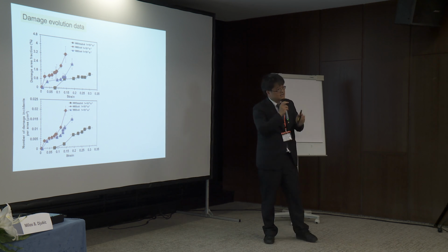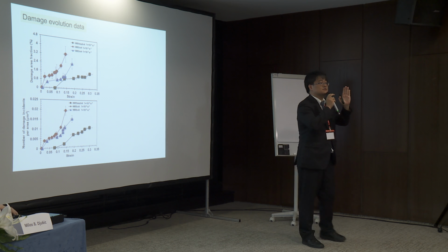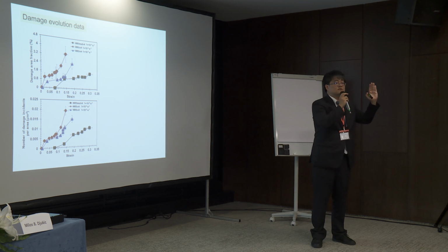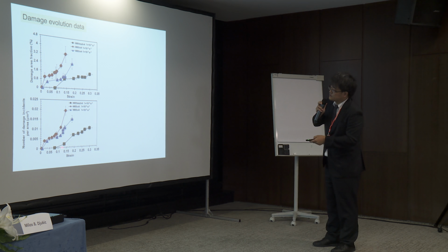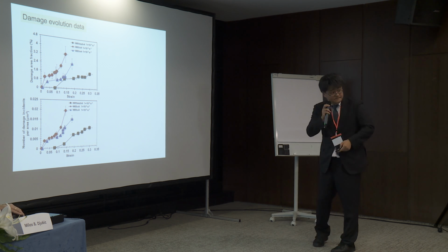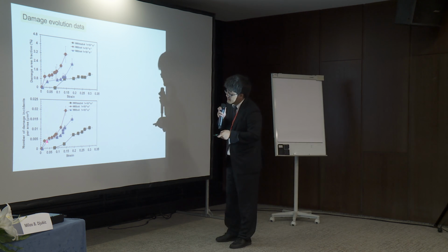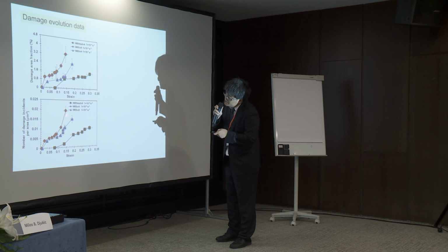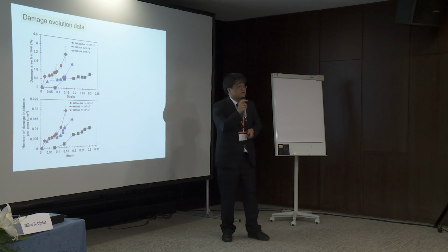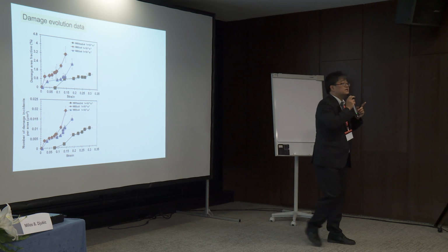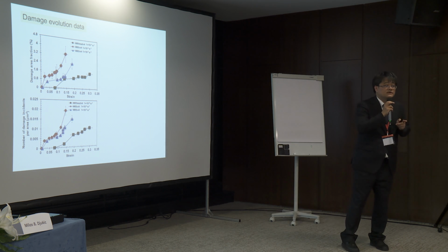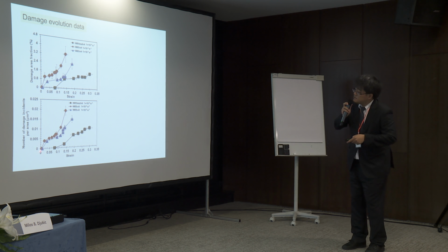Near the fracture surface, there is a large strain, while the grip part has 0 strain. Therefore, we can plot the damage data against a wide range of strain. Here, the most important point is that the number of damage dramatically increased. Damage initiation was promoted. Irrespective of the strain, a huge amount of damage was always observed.